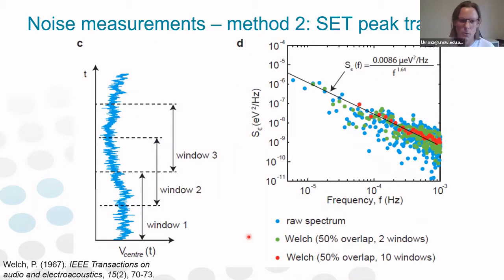What we do here is basically divide our data in time domain into windows. For each window, we calculate the power spectral density independently, and then we average over all the windows. What I'm showing on this plot is the raw spectrum in blue, the Welch method with only 2 overlapping windows in green, and the red data points correspond to Welch data with 10 overlapping windows. So you can see using this Welch method, we can get less variance and a better estimate of our noise, but we sacrifice some of the lower frequency information because we're effectively squeezing the data in the time domain.